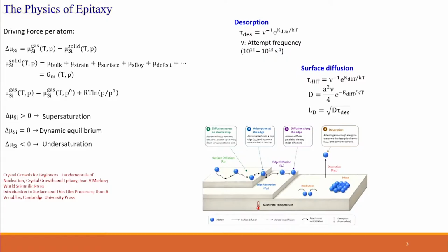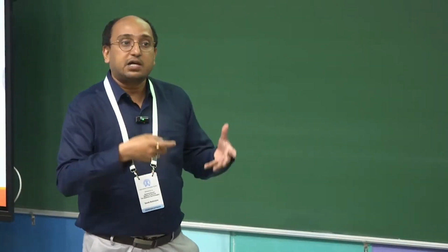So an atom on the surface undergoes, let's say, a 2D random walk. It's a kinetic process, temperature dependent. Diffusion energy is of the order of 1 electron volt. The time scales are of the order of a few tenths of nanoseconds. Whether it's making random walks or hops, it has to find a proper site where it can attach a nucleus.